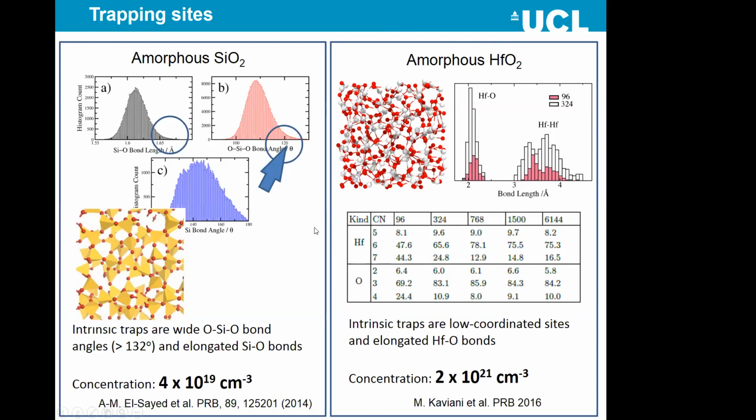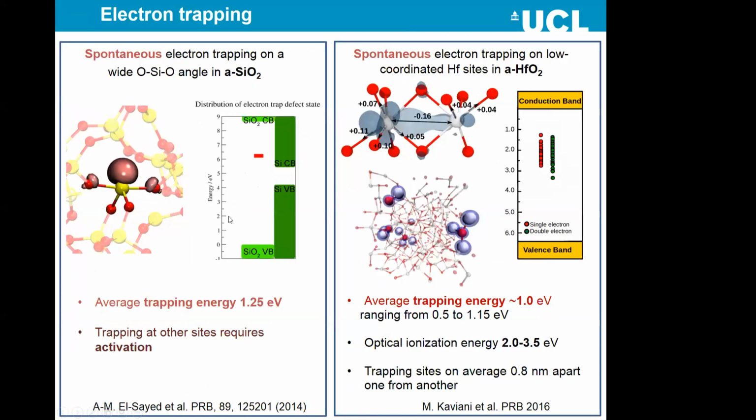So this is what we observe in this system. The results depend on the size of the cells we use, but they converge quite quickly. As a result, we see this type of localized states, which I don't have huge time to talk about, but in all of these amorphous oxides we see hole localization on oxygen p states, and in some cases also electron localization on cation states, if these are p or d metals.